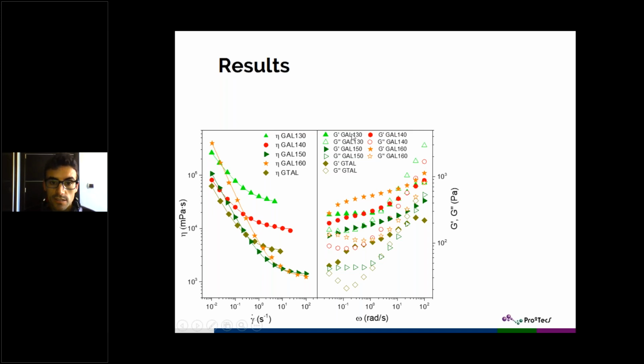For example, for the system with 130 degrees, that is the one that shows the lowest acetylation degree, we can see that both viscoelastic functions are quite close. The viscoelastic functions are high, but both the storage modulus and the loss modulus are really close. We can even see a crossover at low frequencies, around 2 radians per second. So that's telling us that we have not really a well compatibilized system, but kind of a colloidal dispersion, probably as a consequence of that low degree of acetylation that doesn't provide a good compatibilization between the two systems. And also that's raising the viscous